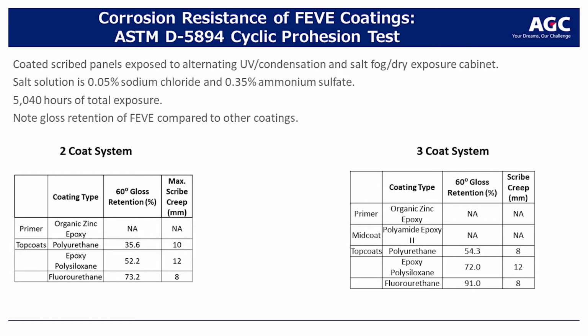There's another test that's run called Cyclic Prohesion. In this test they alternate exposures. They'll put the coated panels into a weathering chamber for a certain amount of time, then move them into the corrosion chamber. Again, they scratch the panels so you're going to get rust in that scribe. They move this back and forth until you get about 5,000 hours of total exposure. What you're trying to see is how the coating performs after it's been exposed to weathering, in other words, to ultraviolet light that's starting to break the coating down.